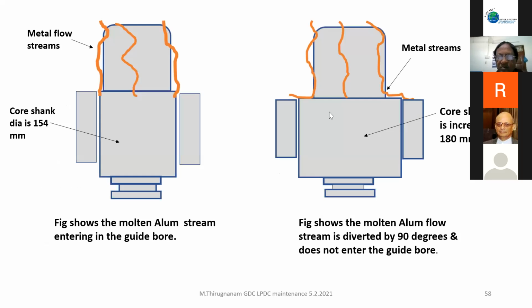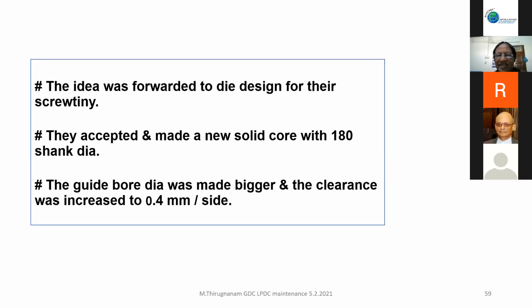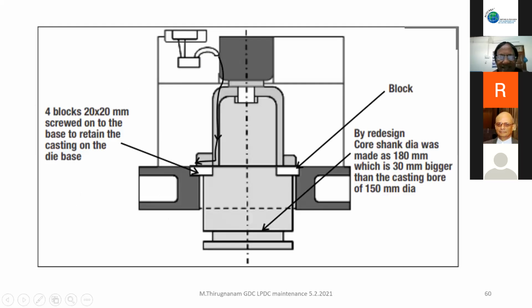So we made the core bigger. See, this core is made very big, 180 mm. This is 150 mm. See, here the metal goes straight into the bore, 0.4. Here, even though the core has 0.4 clearance, the metal will come here and then deflect. So there was no metal entry at all. And the idea was again forwarded to the die design department for scrutiny. They also accepted, and a new core was made with a bigger shank, 180 mm diameter. Again, the guide bore was made 0.4 only, not 0.2. There was no core jamming at all, and it went very well.